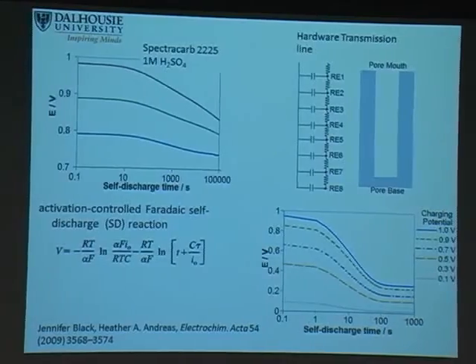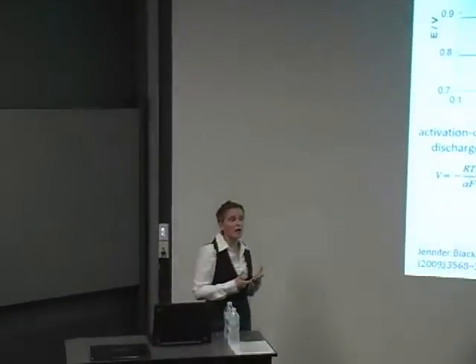And so what we then needed to do was go back to our carbon and say, is there any other way that we could say whether it's charge redistribution or that activation control process? And the way we could do that is by recognizing that if you're looking at the activation-controlled self-discharge, the equation is shown right here, the slope that we see here has no dependence on initial potential. For those of you who know electrochemistry, this equation is based on the Butler-Volmer equation, and we would expect that if it's a Faradaic or an activation-controlled process, at a particular voltage, it should have a particular rate. So if we looked at a particular voltage, let's pick this one right here, we would have the same slope independent of what our potential started at.